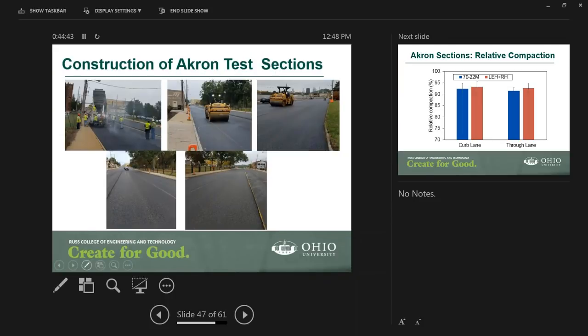In terms of construction, there were no issues related to the GTR. We had some problems at the beginning of the construction because the asphalt mixture was a little bit tender, so the compaction was a little bit difficult at the beginning of the project. But then the contractor adjusted the asphalt binder content. Again, in all cases, the asphalt binder was within the specification. This solved the problem. As we will look at the compaction, there was no problem, but to achieve the compaction they had to roll it several times. But in terms of issues with the construction, we did not see anything.